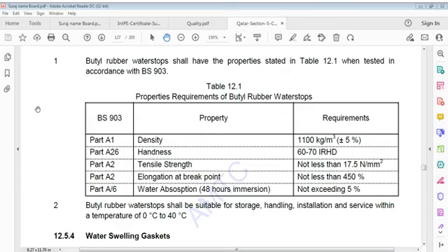And the requirements are: density, that's Part A1, 1100 kilograms per cubic meter plus or minus 5%. That's density. And Part A26, hardness, 60 to 70 IRHD.